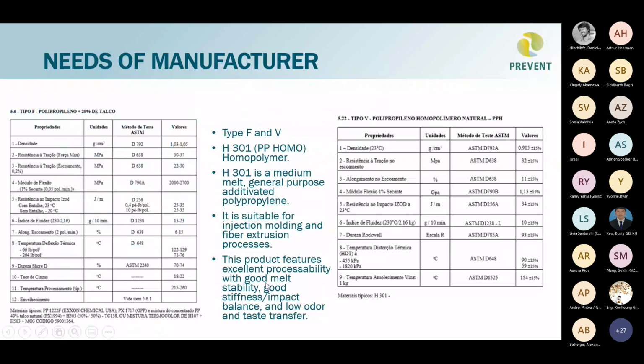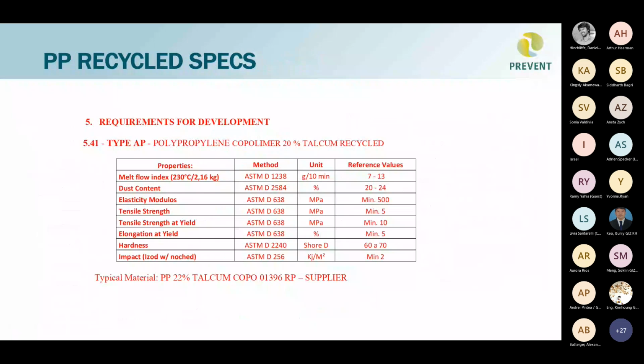So here there are a lot of requests regarding polypropylene with different levels of filler, or also natural. It is considered a material that is very easy for the extrusion process and to inject for the molding process. So it has good processability with good melt stability, good stiffness-impact balance, low odor, and taste transfer. So this is a material that, for the Brazil project, mainly people are looking at the moment. And also here we have more information about the type of plastic with recycled material that could be included.